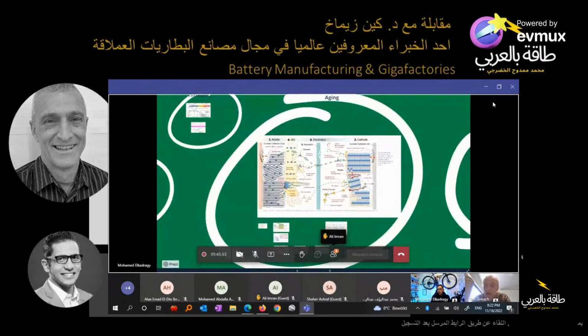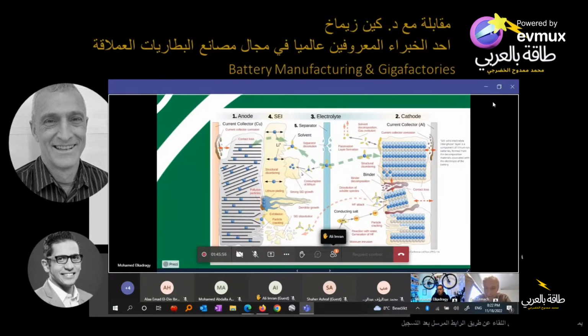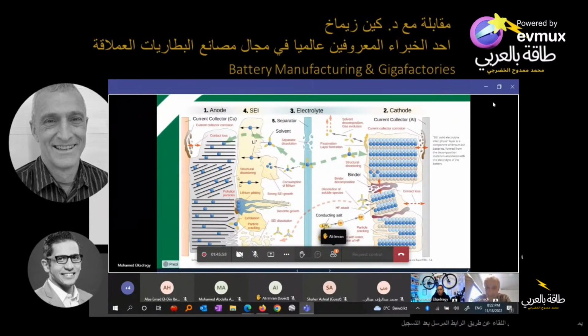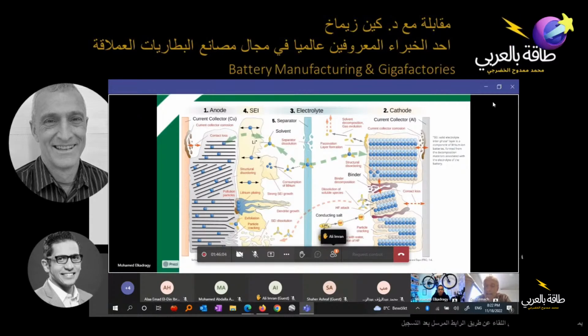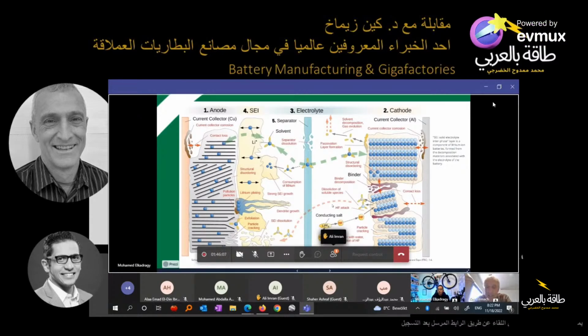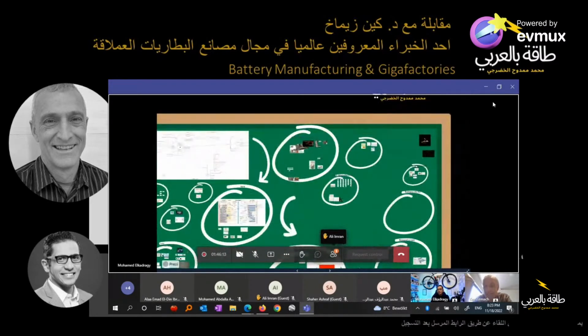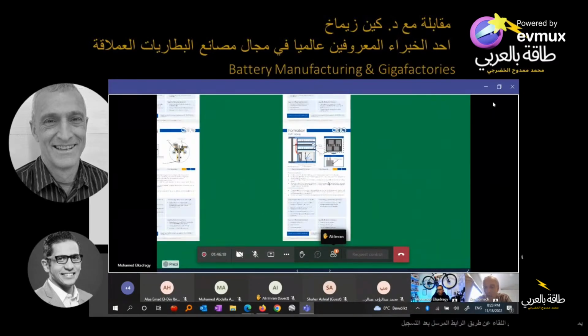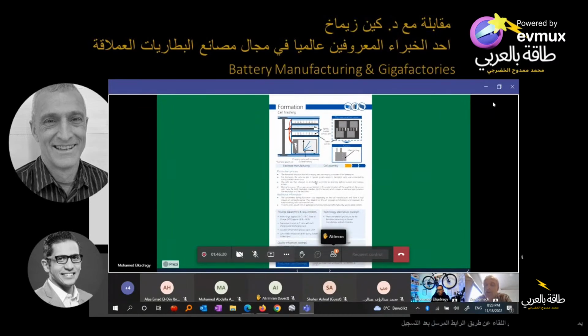But when an SEI is formed, you also get gas given off. The problem is that if you fill your cell, seal it up, and then send it directly into formation and aging, that gas will blow up your cell like a balloon. So you have a degassing phase, which is this pre-charge plus putting it under vacuum to pull the majority of the gas off.